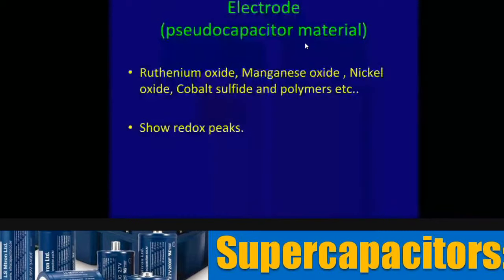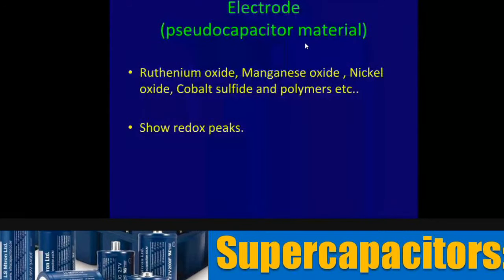Most of us, with whatever amount of chemistry we have learnt at school or probably pre-university and as an allied subject or major subject, will know that the transition metals and rare earth metals have a tendency to show more than one valence state. Especially the transition metals or the so-called iron group metals, they show more than one valence state. That is, when you look at copper, copper can exist in cuprous, namely the monovalent state, and cupric, the divalent state. When you move over to manganese, it is 2 plus and 3 plus, iron 2 plus, 3 plus, whereas metals like nickel can exist in more than 1, 2, 3, 4 and so on.